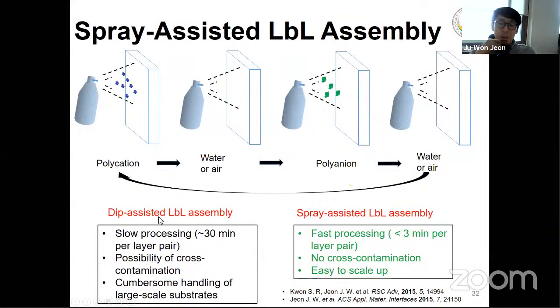So dip assisted layer-by-layer assembly is usually very slow with possible cross contamination. And if you have a large substrate, it is very difficult to dip the very large substrate into the large scale solution. But in the case of spray assisted layer-by-layer assembly, its processing time is very fast. It only takes 3 minutes per layer pair, there are no concerns about cross contamination, and it is easy to scale up because there is no direct contact between the solution and substrate.